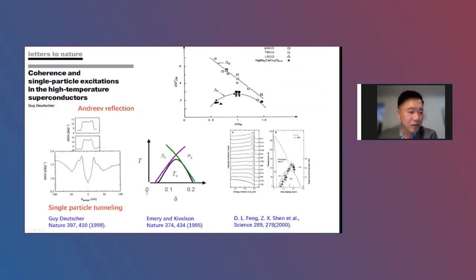Actually, in the cuprates, we have been told many times that the so-called local pairing gap and also the superfluid density determine the so-called Tc dome. This is given by Emery and Kivelson. And also in the ARPES data by Donglai Feng et al., they show this kind of coherence peak follows this kind of curve, okay, showing the Tc correlation.